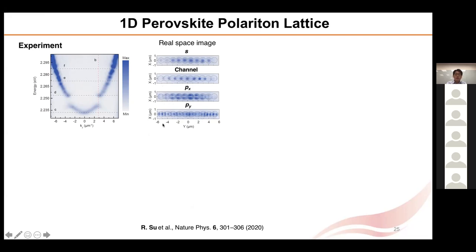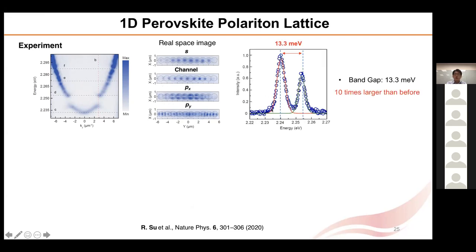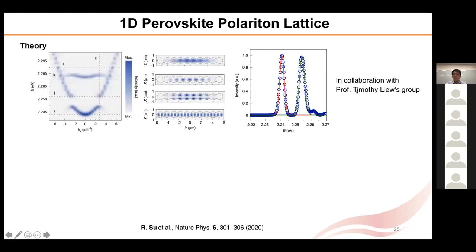To understand more about the gap opening, we take a slice across the gap, as shown here, where we can extract a very large gap opening of around 13.3 meV, which is actually one order of magnitude higher than before. Theoretically, we can reproduce those experimental data perfectly, as shown here, which was actually done by Tim Liew's group.